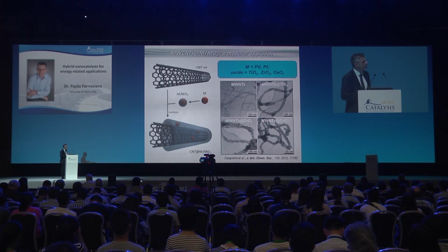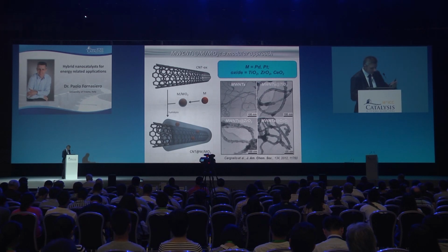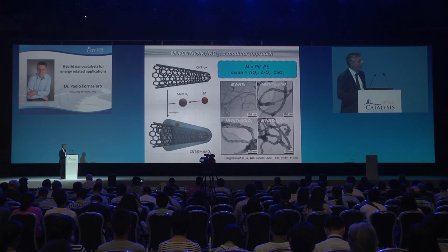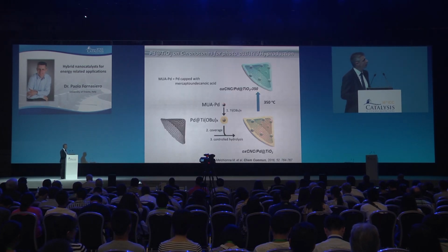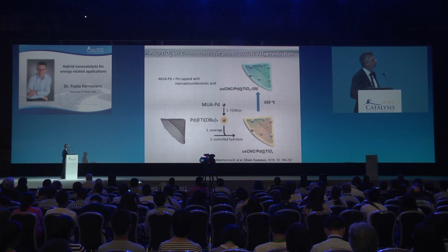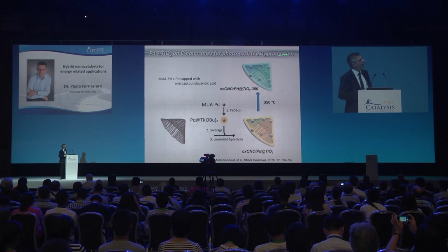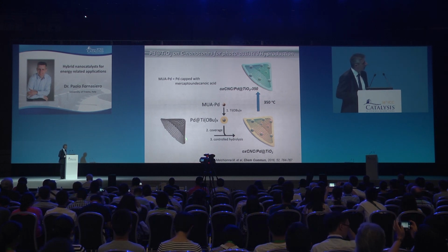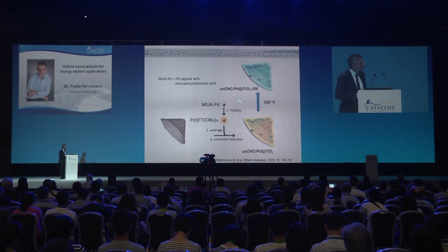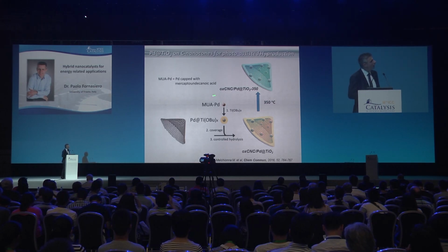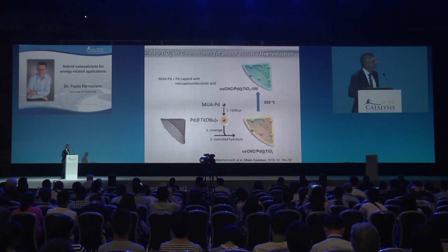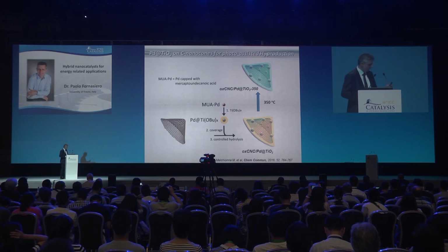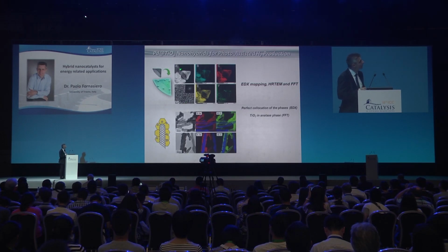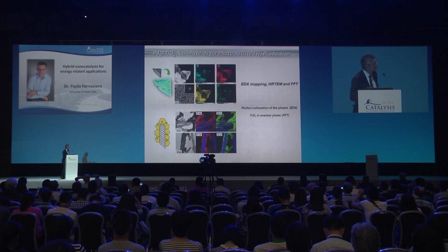So you have to design the approach carefully, and we did it by two reactions. We functionalized the carbon nanostructure nicely, and we were able really to have a homogeneous material. Just to show you a very recent work, we use a fancy carbon-based nanostructure like these carbon nanocones. We encapsulate with our core-shell strategy protected palladium nanoparticles and titanium precursor, and these are really the images of the nanotubes covered by all the components: